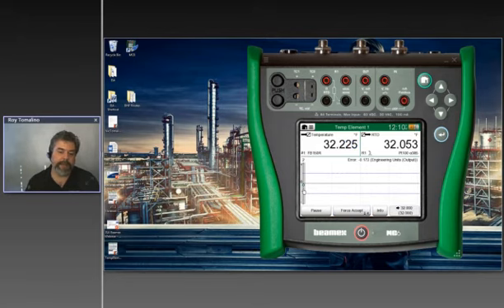We can see our green dot here, and we've got a 5-second countdown, so it's about ready to accept this test point. We have negative 0.172 degrees of error or difference between our probe under test and our reference probe. Now the dry block is heating up, so we'll get to the next temperature, which is in the middle, 122 degrees. So while that's heating up, I'll show you something else, and then we'll come back to this demo a little bit later on.